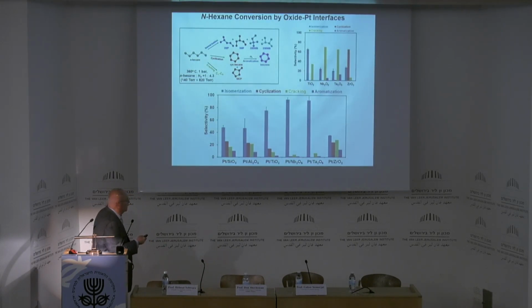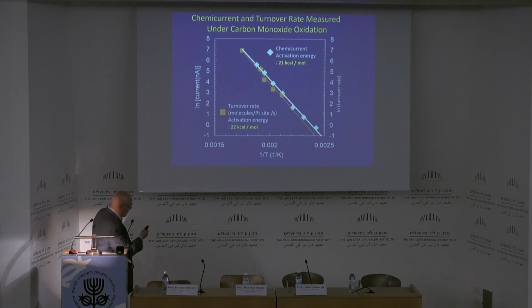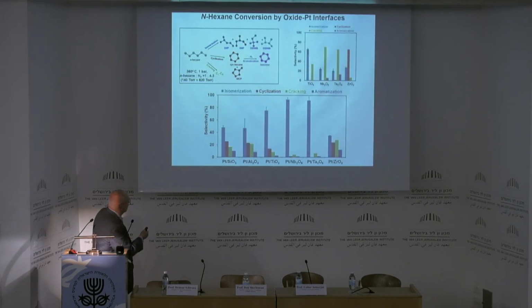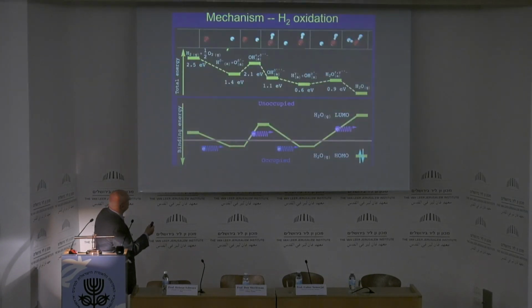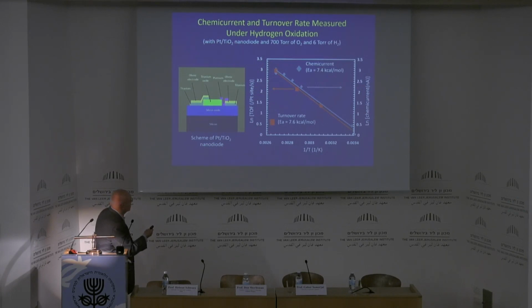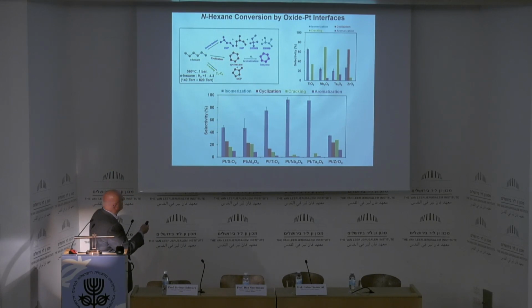And so this is the heart of making high-octane gasoline. If you take N-hexane, and in this case, I apologize. You make the CC bond breaking, and that relates to forming the isomers of high octane with the platinum titanium oxide or niobium oxide interface, and if you use the oxide alone, you don't get much except decomposition. If you use the platinum alone, it's not as good as the oxide metal interface.